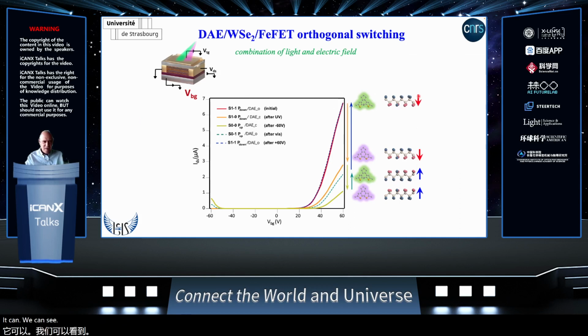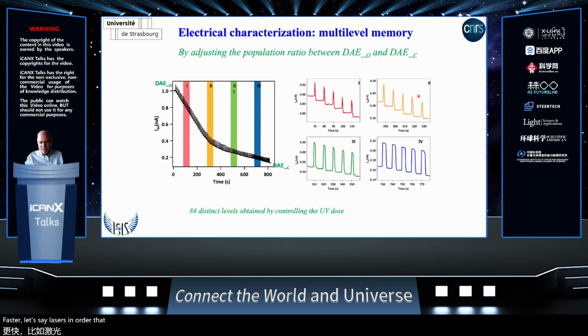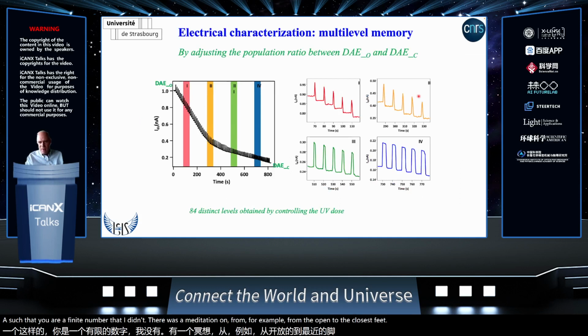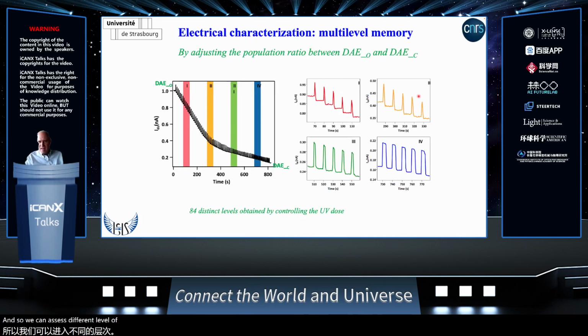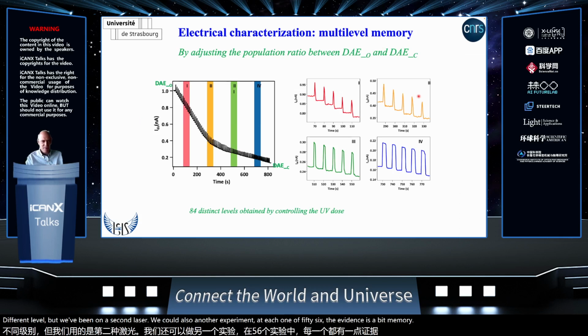we can see here that the two stimuli can actually be used in a simultaneous fashion. So what you can actually do then, you can use fast, let's say, lasers so that each irradiation is such that you have a finite number of diarylethene molecules that undergo isomerization, for example, from the open to the closed state. And so we can assess different levels of current. For example, here, without using the nanosecond laser, we can assess 84 different levels, but with the nanosecond laser, we could also, in another experiment, reach 256 levels, that is 8-bit memories.